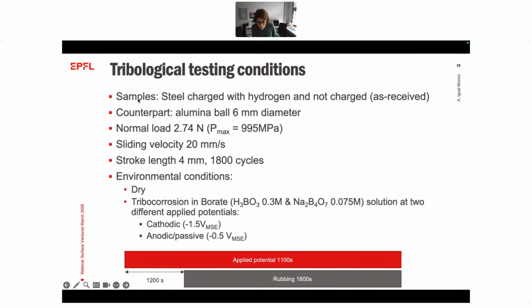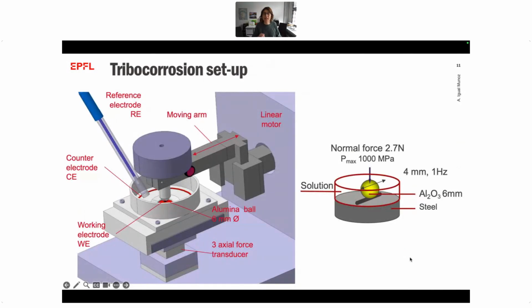So we repeat the same exercise, charging the steel 24 hours. We are going to wear against an alumina ball, 6 millimeter diameter, to impose a certain contact pressure, with a sliding velocity of 20 millimeters per second, stroke length 4 millimeters, for a certain number of cycles. And then what we change are the surface conditions. We did test dry, but we did a tribocorrosion test under well-imposed electrochemical potential conditions, which means cathodic potential. This implies that the hydrogen remains within the material, and then in presence of a surface film we do that applying an anodic or passive potential. So this is the experimental sequence we did, and this is the experimental setup.